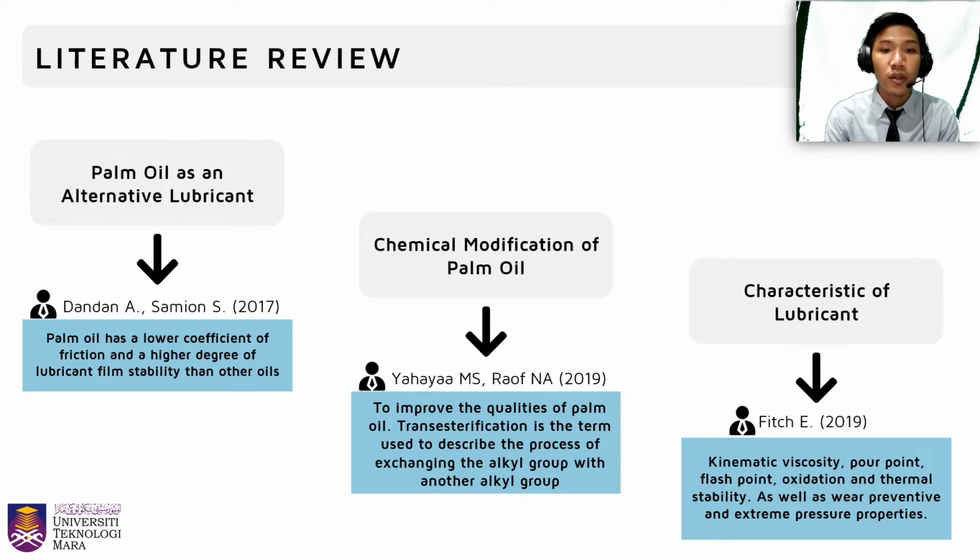Palm ester, which is a product of synthesized fatty acid ester, can be obtained by transesterification. Transesterification can be accomplished in a two-stage acid-alkali catalyzed transesterification method with methanol in the presence of a base catalyst in the first stage and a polyhydric alcohol to produce the equivalent polyol ester in the second stage transesterification.